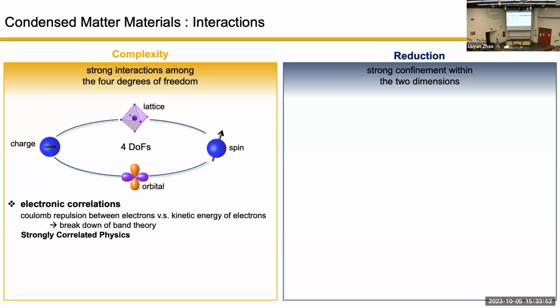So we take an example to see what are the interactions that people especially look into. One example is the so-called electronic correlation, which is defined by the Coulomb repulsion between the charge degree of freedom. Coulomb repulsion is always there for any materials with electrons. But here, there is one criterion. We want to compare this repulsion energy scale with the kinetic energy of electrons. When this repulsion is stronger than the kinetic energy, then it enters into the interesting regime, which is a correlated regime, which makes the collective behavior different from individual electrons' behavior. Okay, that's strongly correlated physics.